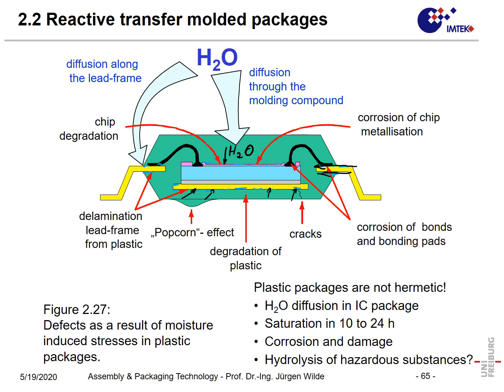And these interfaces now carry a thin layer of water, which is maybe only 1 or 2 molecules thin, but the water is there, and it can have effects both on the adhesion in the system and on the behavior of the package under temperature and temperature shocks. A second way where this humidity can come in is along the lead frames. Here we have an interface between polymer and metal, and that interface means in the polymer we have a disturbed region where more water can be stored and where more water can migrate along.